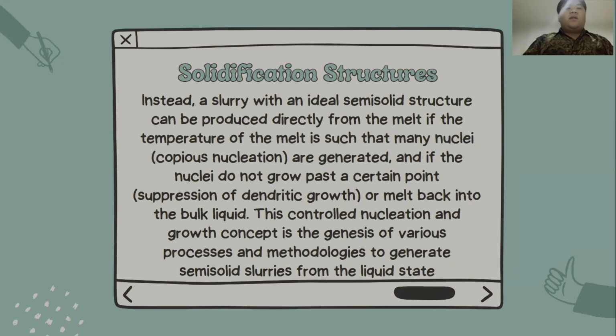Instead, a slurry with an ideal semi-solid structure can be produced directly from the melt if the temperature of the melt is such that many nuclei, or copious nucleation, are generated, and if the nuclei do not grow past a certain point, through suppression of dendritic growth or melt back into the bulk liquid. This controlled nucleation and growth concept is the genesis of various processes and methodologies to generate semi-solid slurries from the liquid state.